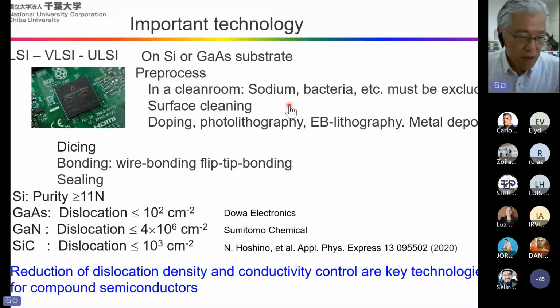And for the materials, silicon and gallium arsenide are very advanced crystals, and silicon has a very high purity, more than 11 nines. The gallium arsenide crystal quality is far lower than silicon, but it is far better than gallium nitride and silicon carbide. So the dislocation density is 10 to the 2nd, and for gallium nitride, at present, it is in the middle of 10 to the 6th.